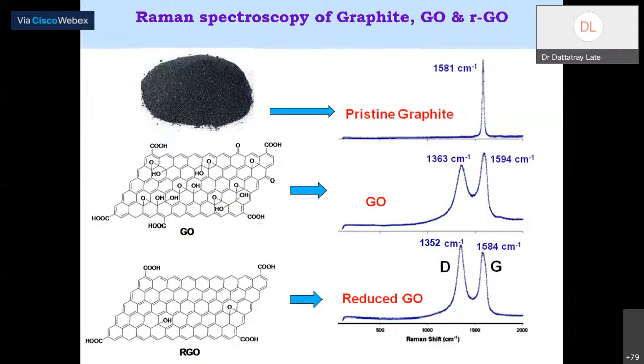Okay, again, once we have the very surprising thing, this graphite powder, graphite oxide, reduced graphite oxide, all are black in color. Suppose someone has given you these three samples, how can you distinguish them? Because they are the same in color. You take bulk graphite, and in bulk graphite you will get a single spectrum of the G band, which appeared around 1581 centimeter inverse. You can see a very nice spectrum for this particular pristine graphite sample, right?